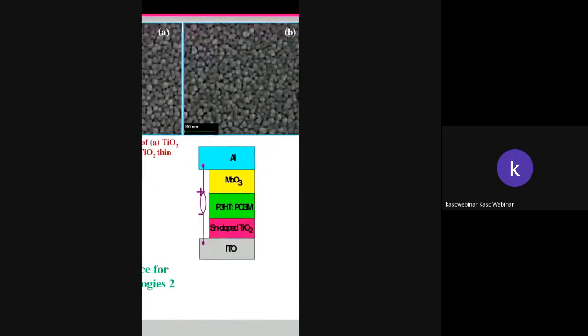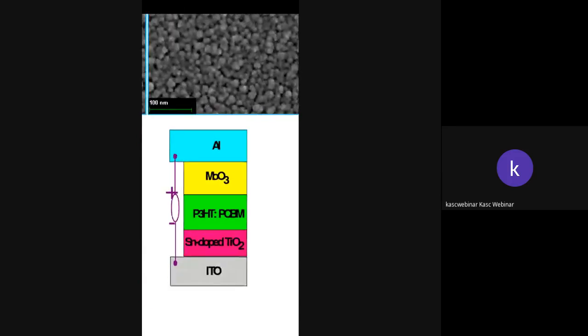And the device architecture is shown in the block diagram. First, the ITO substrate. Above that, the doped TiO2 thin film is used, and P3HT:PCBM is coated over that, and molybdenum oxide and aluminum is used as a contact.